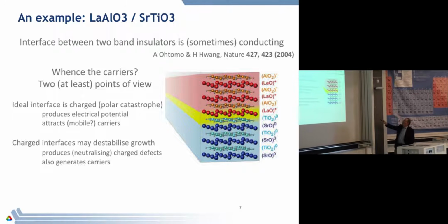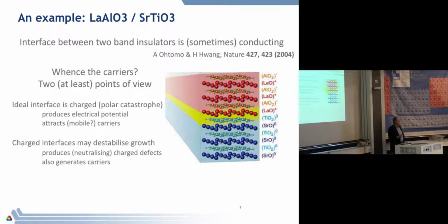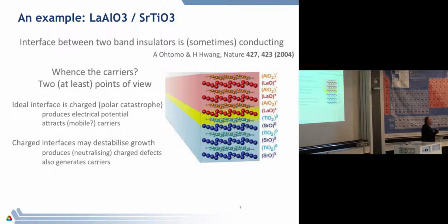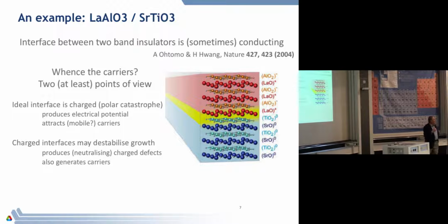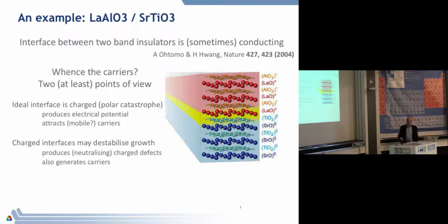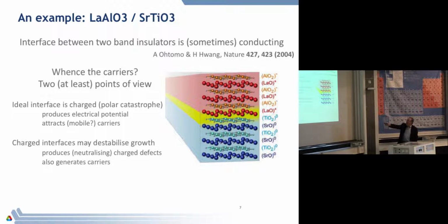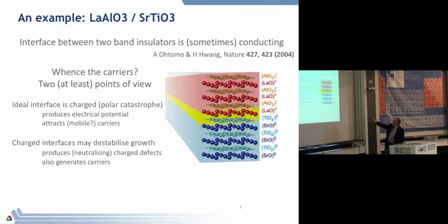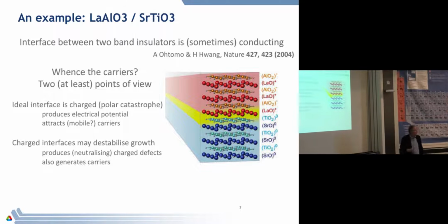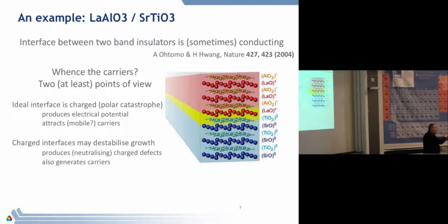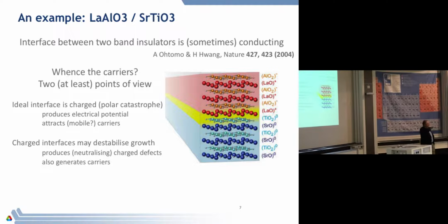But if you go up to the top to lanthanum aluminate, which has exactly the same structure, the formal valence that you would normally associate with lanthanum and with aluminium is 3+. And so that means that the lanthanum aluminate layer here is formally positively charged. The aluminum oxide layer is negatively charged. And you see, as I go from neutral layers to layers which are now positive, negative, positive, negative, there is a dipole forming in here just because of the way that I ended that surface.